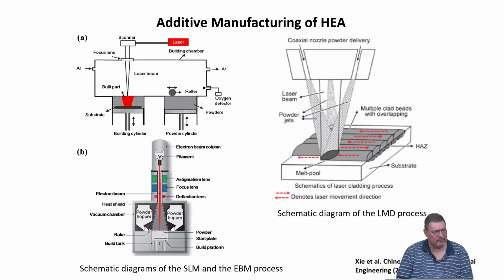Additive manufacturing is very hip these days, and everybody investigates it. It is basically similar to laser cladding, right? I mean, you can not only use lasers, you can use all kinds of energy sources in order to do the additive manufacturing. I think most people using high entropy materials use laser-based processes, powder bed fusion. So you basically have a powder of your material you want to make a structure out of. You put it down in a layered fashion, and then you scan with a high power laser in the regions where you want to create a structure. It melts, it freezes, and you take the rest of the powder off. You can even reuse it, and only the structure is created in positions where it should be. So you don't need to machine out material, especially for high cost materials like high entropy alloys. This is a favorable way to go.